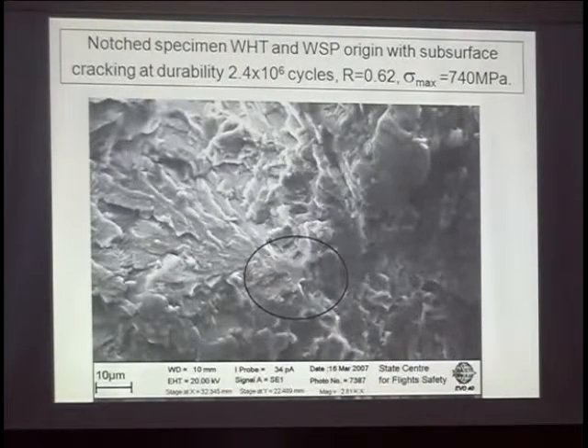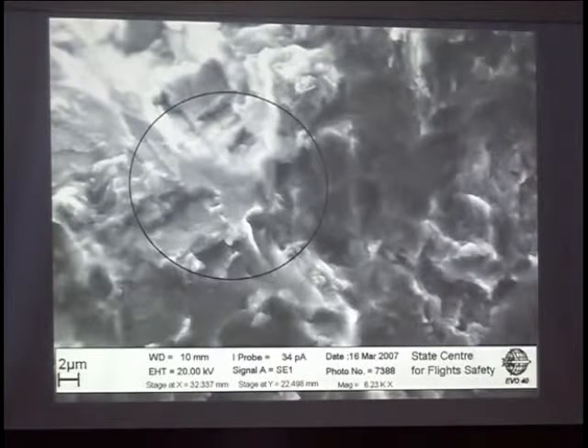For the notched specimen, also very clear, first of all, a facet of weakened material. Out of this facet can be seen very strongly expressed material cracking out of this area. At higher magnification, you can really see that it's a very, very smooth facet, but around it there is specific material cracking, because it was material that has been used for specimen manufacturing from the discs that have been prepared by the well-known technology used to prepare discs in aircraft engines.